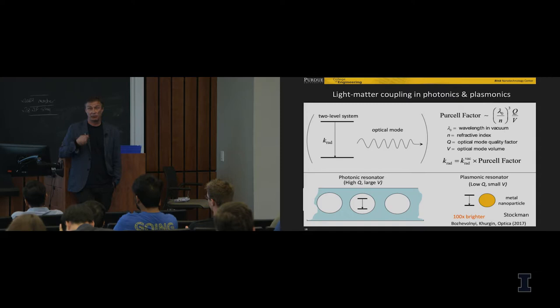We come back to the same problem. I mentioned that you have these very slow rates which you would like to speed up. Therefore, what we propose is that instead of going to high Q, let's use modest Q, like 100. And that brings me to plasmonics, in the heart of metamaterials. With plasmonics, you have all types of resonances, like antenna-forming metasurfaces, and the quality factor would be around 100. But the volume where you confine electromagnetic radiation could go way beyond the diffraction limit.